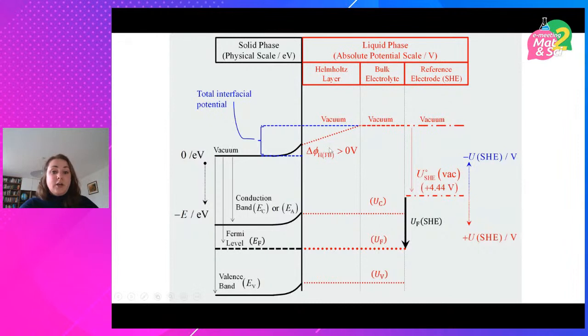So in this picture here, we have a higher, more alkaline pH than the pH PZC, and so you have this kind of potential drop across the Helmholtz layer. The gradient would be reversed if we were in more acidic solutions. The only case when there would be no potential drop across the Helmholtz layer would be at the pH of zero charge. So a very specific condition, which doesn't really coincide with the conditions under which, for example, hematite is usually employed.